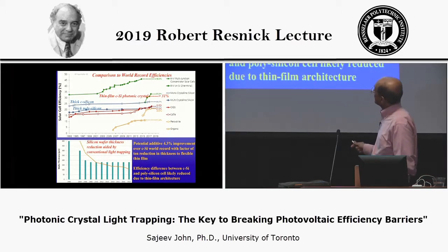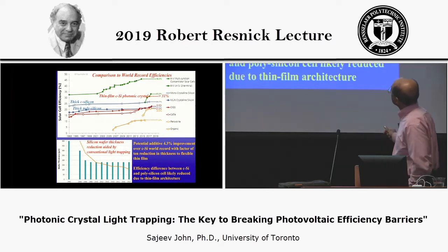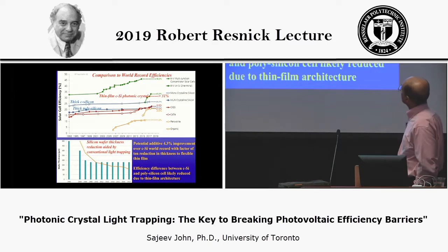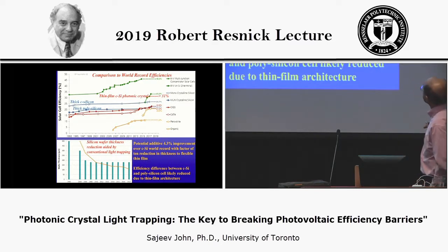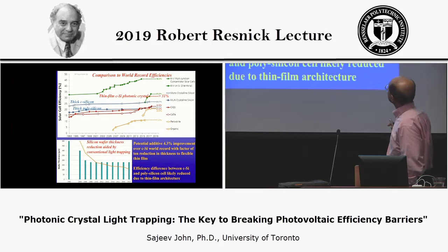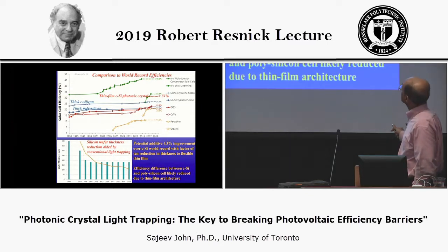This is thick crystalline silicon, monocrystalline silicon, and then thick polycrystalline silicon. You can see that over many years, the efficiency has increased only slightly, but not by a dramatic amount. And then there are these other materials that are competing with that for the thin film space, the CIGS, cadmium telluride, and the perovskites that are very close to the thick polysilicon case.